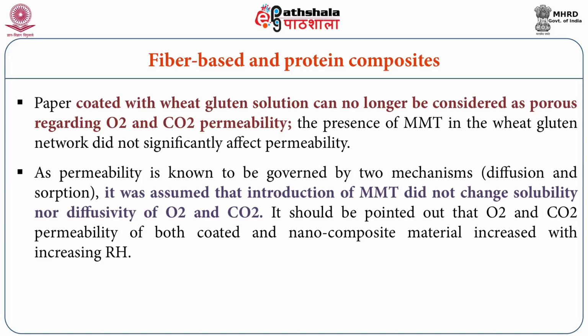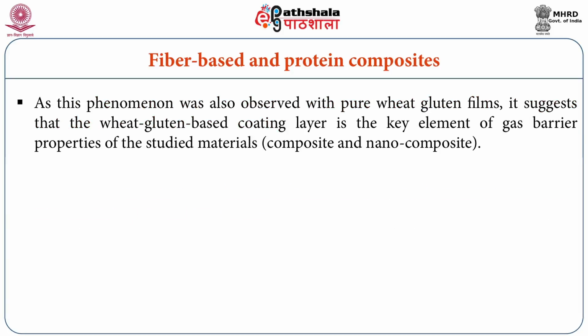It should be pointed out that oxygen and carbon dioxide permeability of both coated and nanocomposite material increased with increasing RH. As this phenomenon was also observed with pure wheat gluten films, it suggests that the wheat gluten based coating layer is the key element of gas barrier properties of the studied material, whether it is composite or nanocomposite.